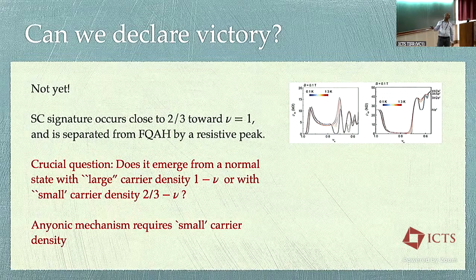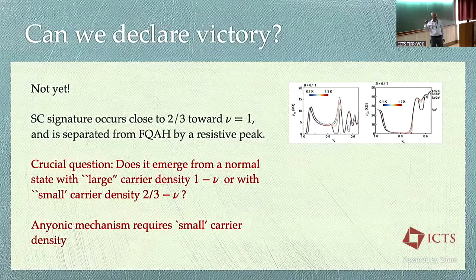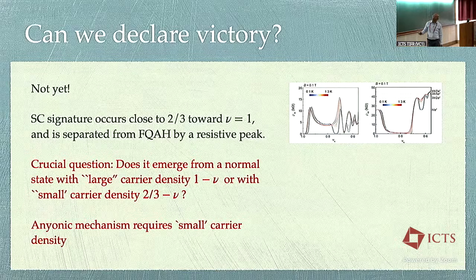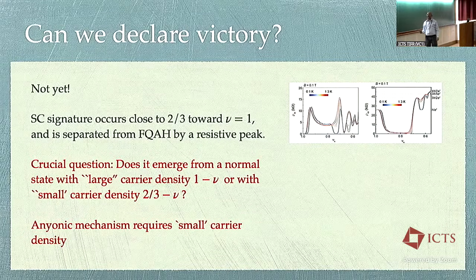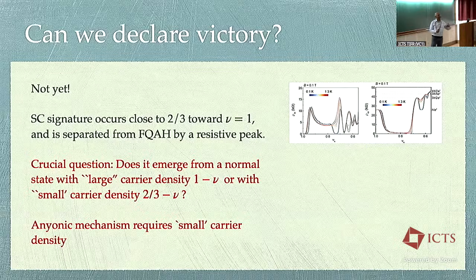And can we declare victory, right? So I don't think we can declare victory yet. A lot more experiments are needed. In particular, there is a really important question as to whether the normal state out of which the superconductor emerges has a mobile carrier density given by 1 minus nu, the deviation from integer, or whether it's given by the deviation from 2/3, right? If it's the former, then the right picture is not that of doping the quantum Hall state, but instead doping the integer quantum Hall state and having a Fermi surface, which then has an instability. So the anyonic mechanism requires a small carrier density. Again, similar issues, people who work on cuprates know these issues very well.